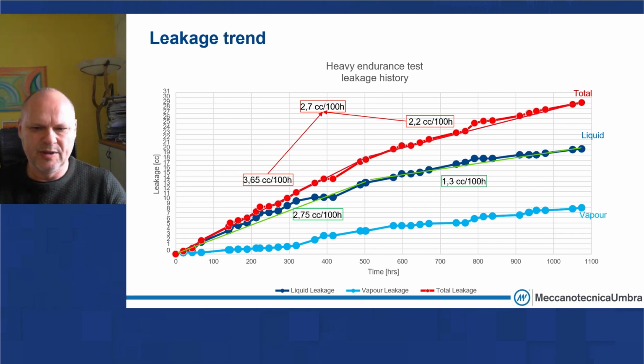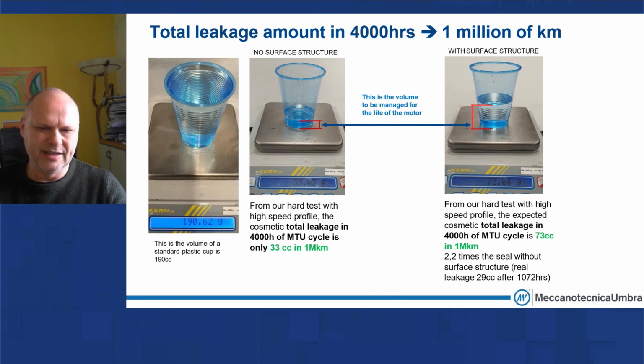What does it mean in terms of managing of leakage? So if we place the leakage we obtain in a plastic glass, we can see that a full plastic glass is more or less 190 cc. The leakage we obtained in 4,000 hours with the first solution is something like this. So we have 33 cc in 1 million kilometers. This amount of leakage, that is the sum between liquid leakage and condensed vapor, must be managed inside the electrical motor. It's not a big quantity, but it's a quantity that must be considered during the design of the sealing area of the electrical motor.